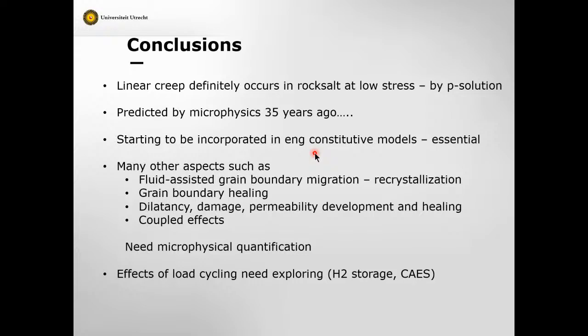And I think more and more people believe that it is indeed by this mechanism of pressure solution, which I'm pleased to say to those that have doubted it, we actually predicted, myself, Janos Urai, and a number of other people, we predicted this effect 35 years ago, and now it has been measured in real natural rock salt under confined conditions by the fantastic work at the Institute of IFG in Leipzig in Germany. It was wonderful work. And at the École Polytechnique in France, Pierre Bérest and colleagues did fantastic work.